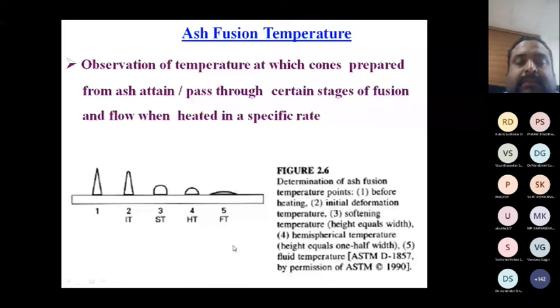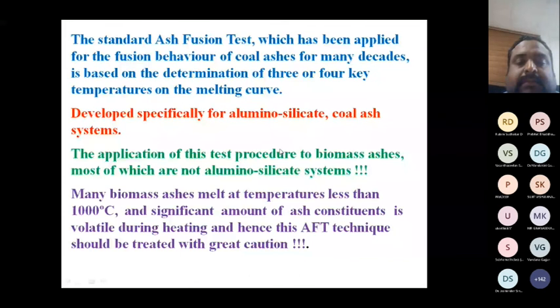The standard ash fusion test, which has been applied for the fusion behavior of coal ashes for many decades, is based on determination of 3 or 4 key temperatures, whatever I told you: initial deformation temperature, softening temperature, hemispherical temperature. It was developed specifically for the aluminosilicate coal ash system. The application of this procedure to biomass fuels, most of which are non-aluminosilicate, you can see, biomass has no alumina, so biomass is a non-aluminosilicate ash. So you have to make a very cautious approach in the application of the technique to biomass.